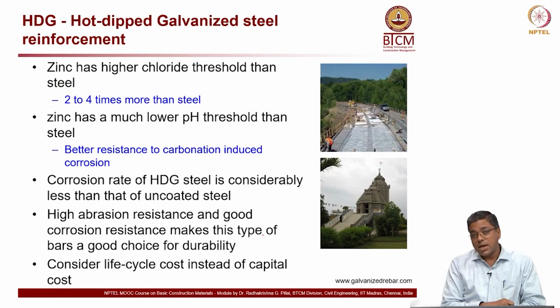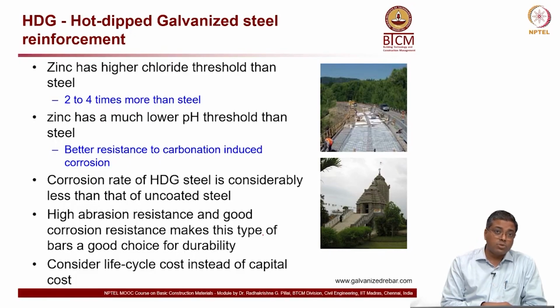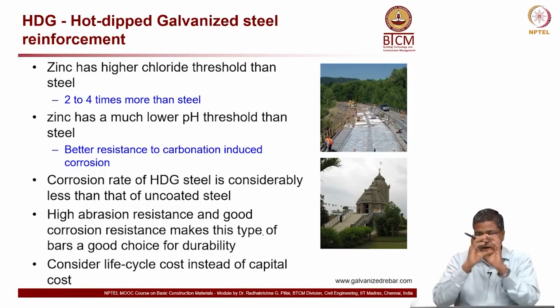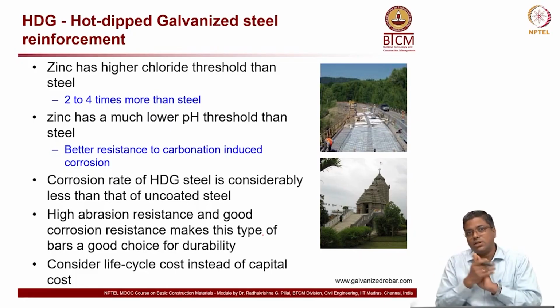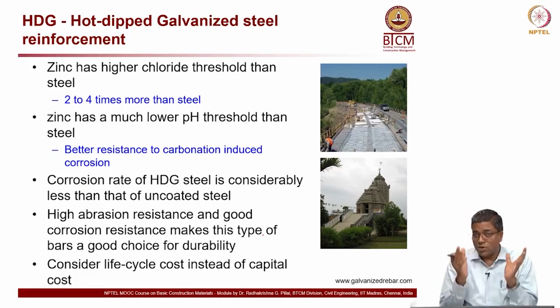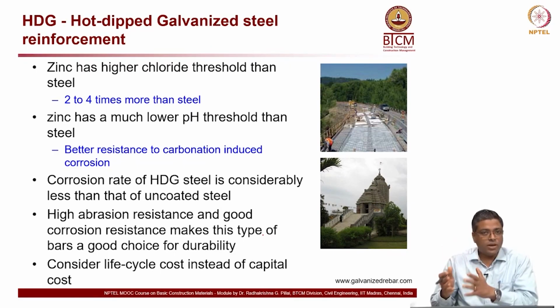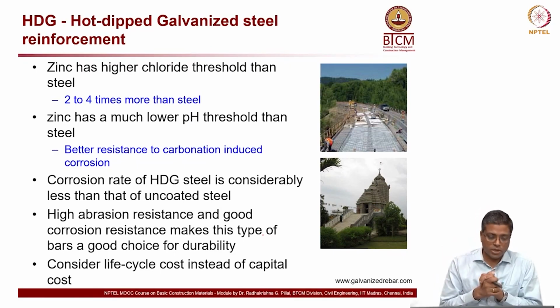Also, zinc has a very high chloride threshold. In other words, zinc will need 2 to 4 times more chloride contamination to corrode. So when you put galvanized steel in concrete, it will need double or 4 times the amount of chloride for that steel to start corroding, because only after the zinc coating corrodes will it reach the steel. If the zinc coating is preventing corrosion, definitely the steel inside is also getting protected.